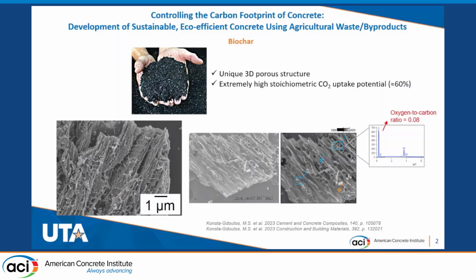Biochar exhibits a unique porosity, and also, due to its aromatic structure and ultra low oxygen to carbon ratio, biochar can exhibit an extremely high stoichiometric CO2 uptake potential of around 60%. So the combination of this porous structure and the high stoichiometric CO2 uptake potential of biochar make this material